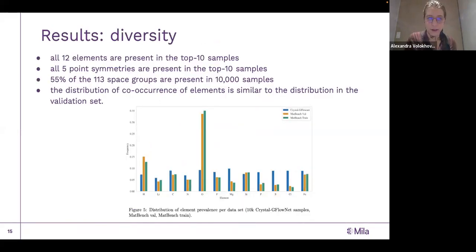Okay, and the other analysis is the diversity. As I said, we expect GFN to sample a diverse set of samples, and in our experiments we found that in the top 10 samples according to the reward, so the lowest energy crystals which GFN sampled, all the 12 elements are present, and all the 5-point symmetries are present in these top 10 samples. And also in 10,000 samples, there are 55% of the space groups which are possible to sample.